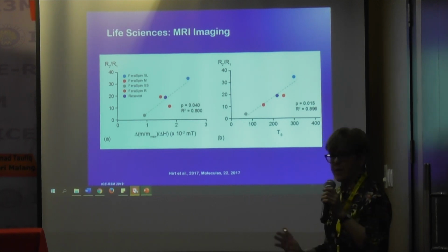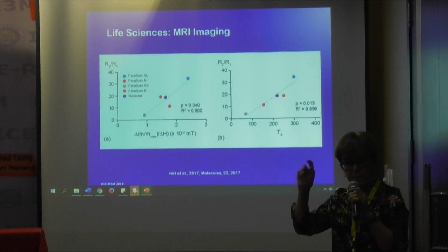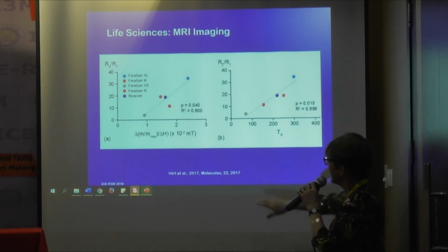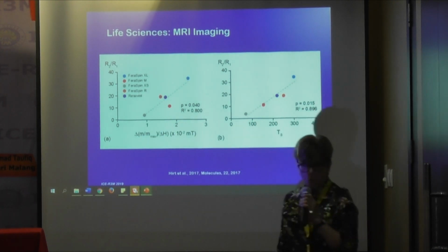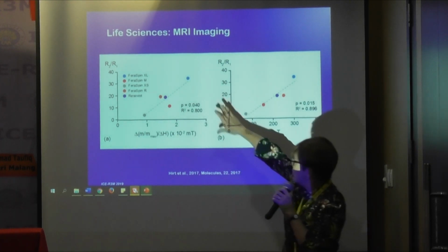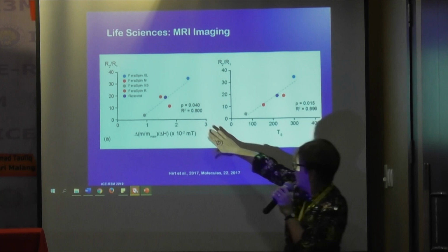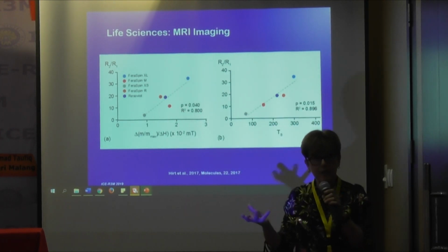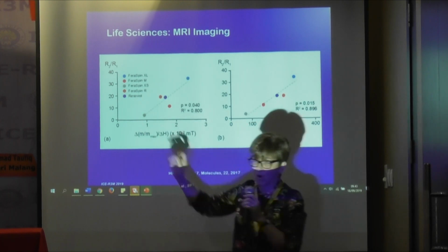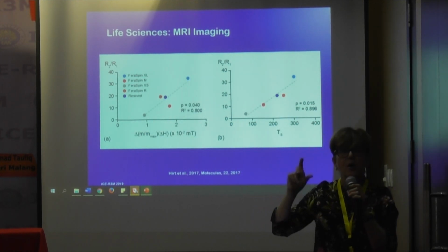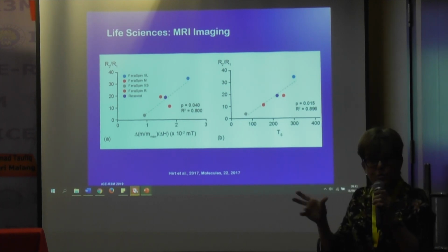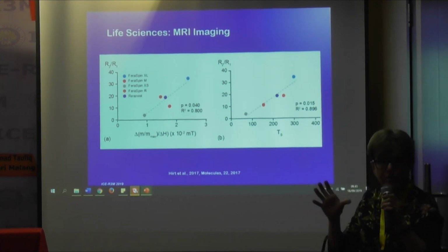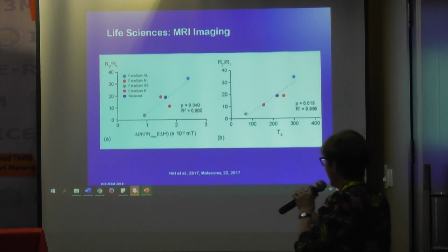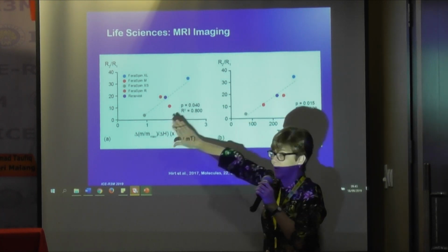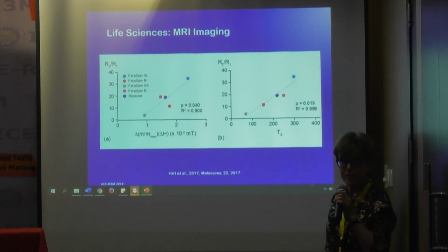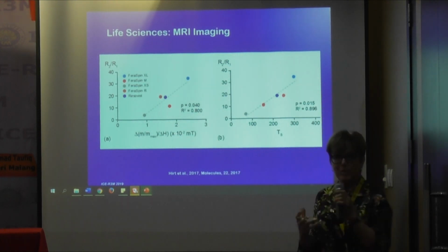And what we did is we did two things. We first took the initial slope, so just in very low fields, what's the slope of the hysteresis curve? We saw the small particles had very low slope, the large particles had the highest slope, but everything in the middle sort of fell here. So it was diagnostic. And this here is R2 over R1. These are the relaxivity ratios that you use in MRI to tell about contrast. The higher this ratio, the better the contrast. And sure enough, the one with the highest susceptibility has the best contrast. The one with the lowest susceptibility has the least contrast. But in the middle, it sort of fell apart. And we were disappointed by this.